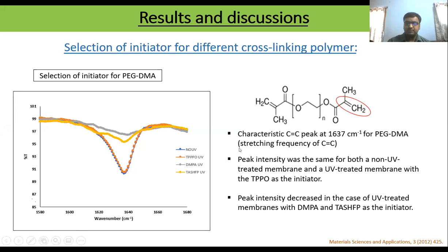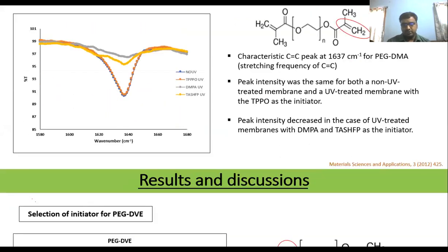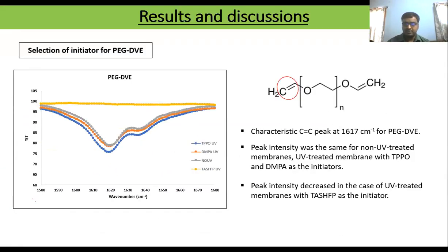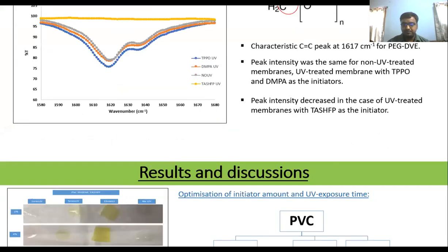In the next step, we did it for another cross-linking agent, PEG-DVE. From here, you can see only the TAS HFP initiator worked and did the complete cross-linking. So the moment the peak at 1617 centimeter inverse disappears, this is the corresponding peak. So from here, you can say this PEG-DVE is cross-linked by TAS HFP.